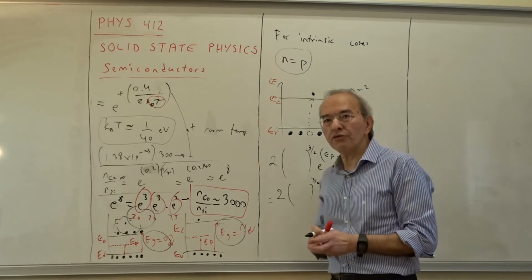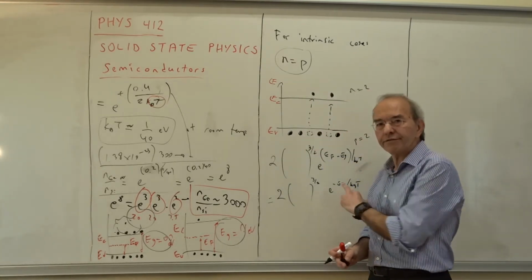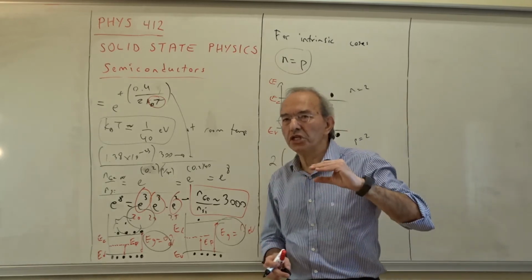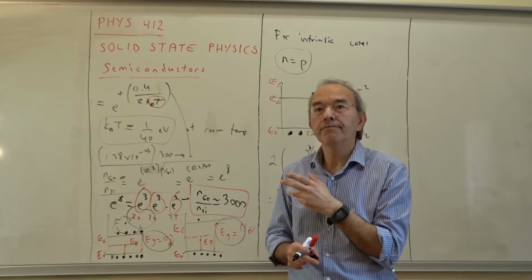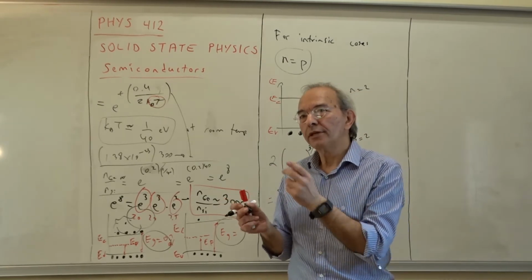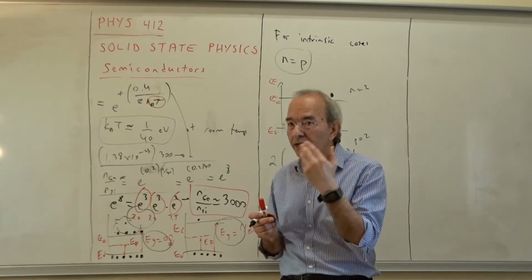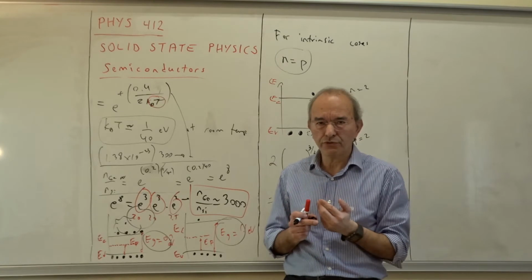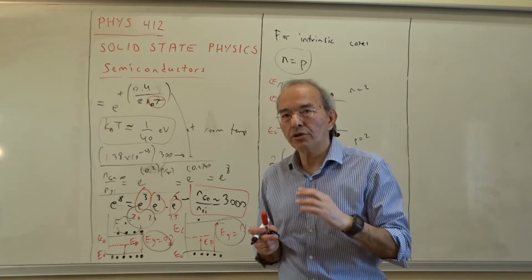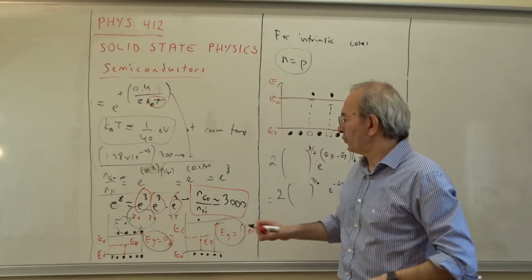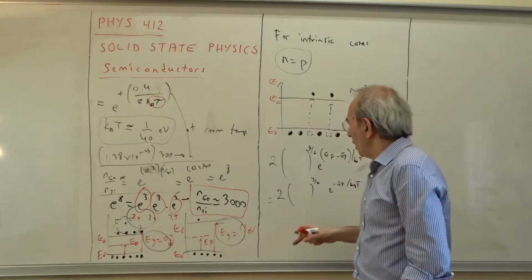From this equality we obtain, remember in the previous lecture, the Fermi level EF. It corresponds to half of Eg plus some additional term. That additional term was an ln function. And ln of what? Ln of the ratio of the masses, mass of electron, mass of hole. If they are assumed to be the same, for simplicity, then ln 1 is 0, so it is just the midway between these energy levels. This is one way.